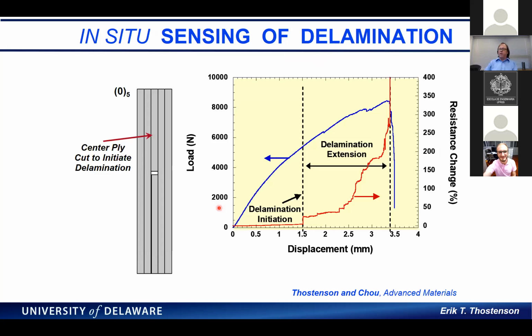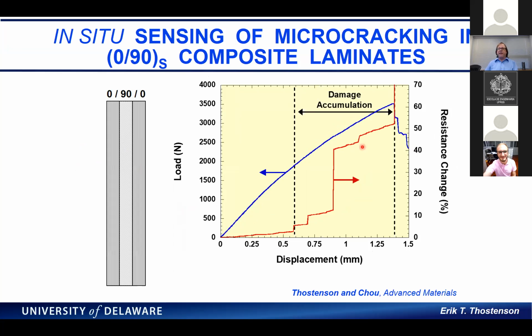These are the very initial experiments where we looked at delamination, where we cut a center ply, and we could very clearly see the initiation and extension of delamination when we were loading this specimen in tension. And then we made a cross-ply laminate. And this was also very clear. At some point, you saw these jumps, and this was really that damage accumulation where you start getting transverse cracks, and then those transverse cracks start accumulating in the 90-degree ply, and then eventually lead to either interfacial delamination or fiber fracture, and then specimen fracture.